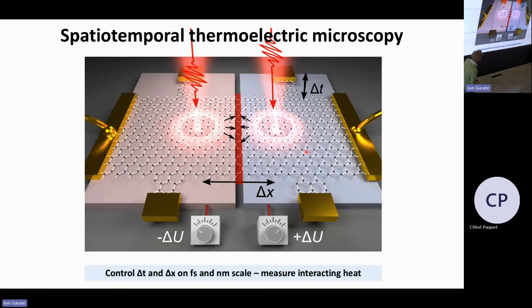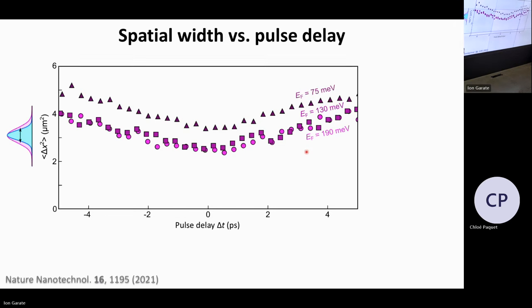So basically we're going to change both the spatial and the temporal offset of these two pulses. We're going to change the delay in time, and we're going to change symmetrically the offset with respect to this junction. You can already imagine that if you make delta X really large, so you're exciting very far away from this junction, it will take more time to reach this junction where the photovoltage is generated. Another way to see it is that the higher your diffusivity, the faster it creates a photovoltage. So this is how we're sensitive to the diffusivity in the system.